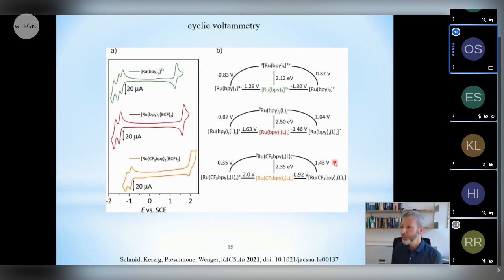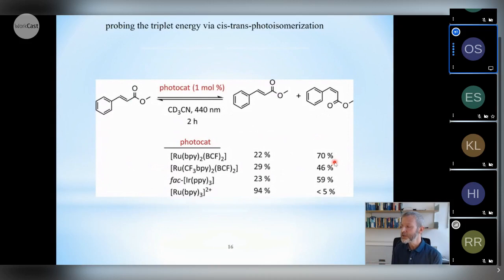complexes. So you get a first test reaction here for the triplet energy. This is a fairly trivial trans-cis photoisomerization of this methyl cinnamate ester, which cannot be performed by Rubpy because the triplet energy is too low. You can hardly obtain any of the cis product. But with the cyanoborylated ruthenium compounds, this now works nicely, perhaps even better than with some of the iridium complexes. So that's just the first test.